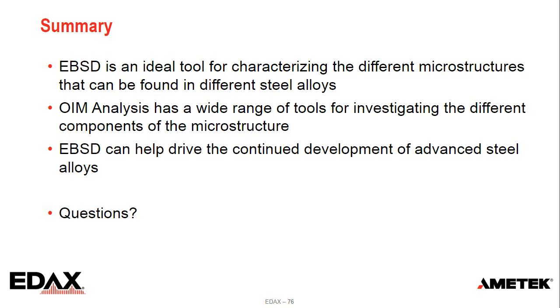Here's a question: are there some measures to improve the image quality of the deformed sample in EBSD? Yes, there are. Defining "improve" is a little tricky. For all cases, sample prep is really important. You want to at least make sure what you're measuring is as representative of the true sample as possible. So the best sample preparation will help improve your image quality, and then any decrease in image quality corresponds to the true microstructure. If you have a deformed material, your image quality will be less than if you had a recrystallized material, and you want to be able to tell that.